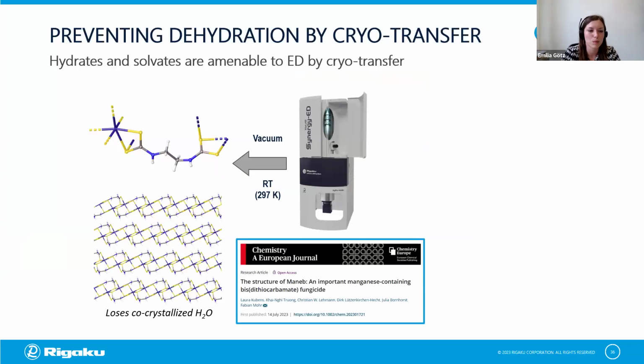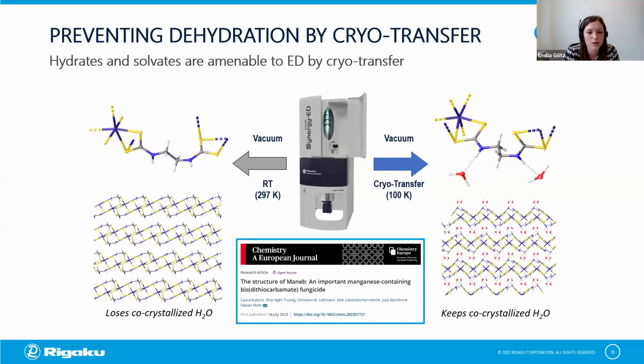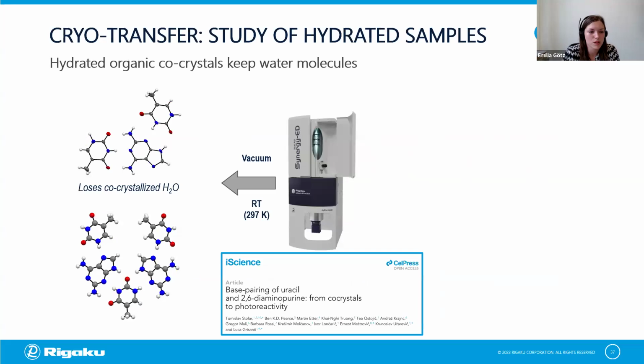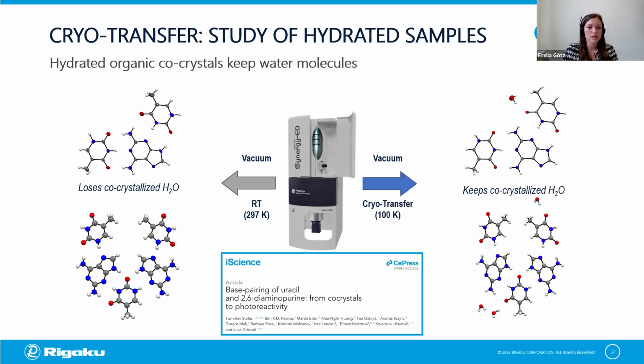So let's have a look at a couple of examples for cryo measurements. In this structure, which was published by Kubens et al., we can see a fungicide, which looks like this when measured at room temperature, so with no water in it. But when measured at 100 Kelvin after cryo transfer, we can see that the water stayed in the structure and the structure is actually slightly different as well. So we can prevent the dehydration of the structure with cryotransferring the sample. And another example of this was published by Stola et al., where again, the co-crystallized water was lost at room temperature measurements, but stayed in the co-crystal when doing a cryotransfer and measuring at 100 Kelvin.